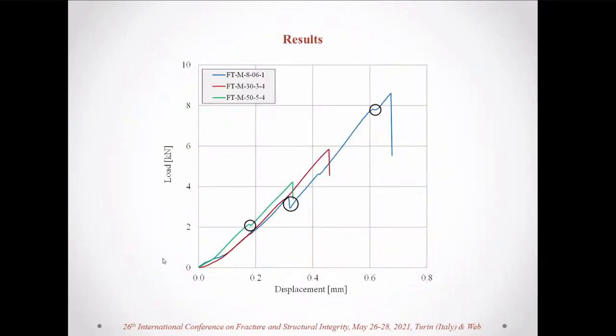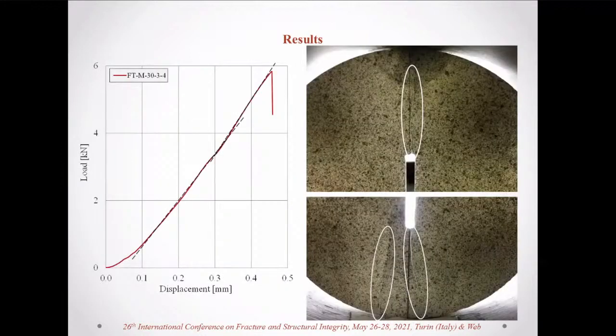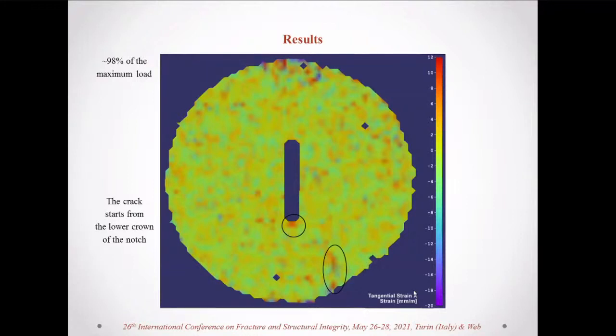These are typical load displacement curves, one curve for each class of specimens. And it is seen that almost all of them exhibit some load drops, one or more. Let's focus on a typical specimen of the second class. This photo was taken right after the fracture of the specimen. We can see at the upper part of the disc a unique crack along the loading axis, while on the contrary, at the lower part of the disc, there are 2 cracks. So we tried to find out from which crown of the notch cracking started.